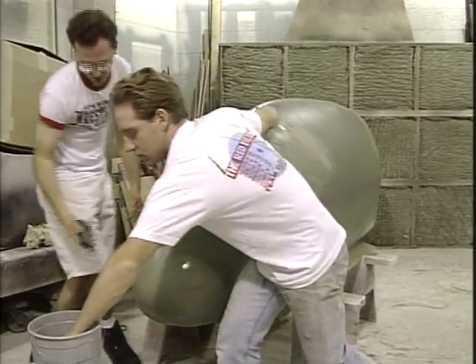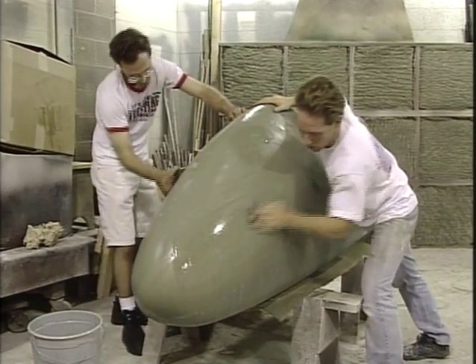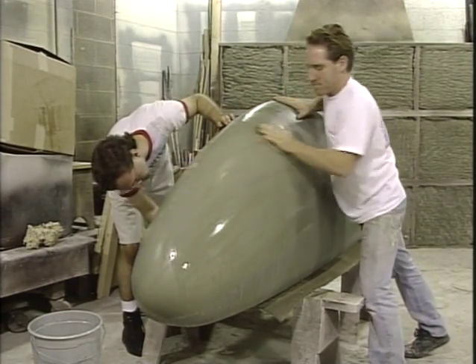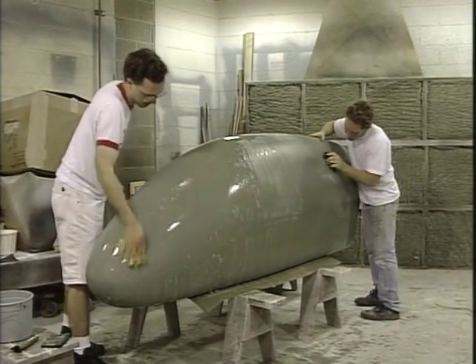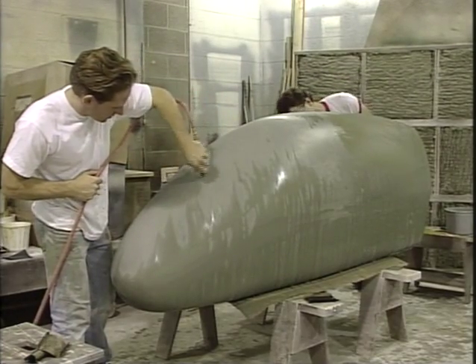While the surface may appear fine, a closer inspection usually reveals a slight orange peel texture. This texture, along with any other minor flaws, must be sanded off the plug or it will be transferred to the mold surface. Begin using 240 grit wet sandpaper and a wet or dry sanding pad. Clean the paper frequently with water to remove dust and to lubricate the plug's surface. Rinse the entire surface with clean water, dry, and inspect.